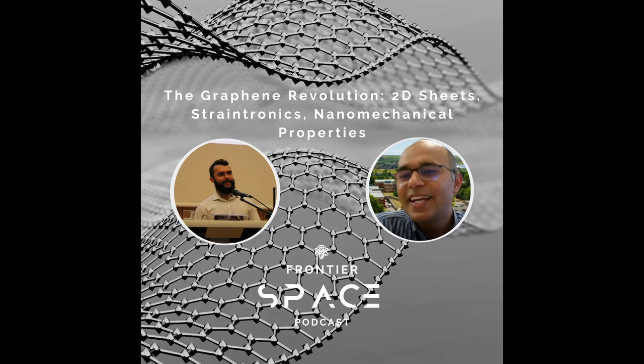So if you increase the structural disorder, the temperature will rise, but there should be a limit, because it is eventually a carbon material, and when you're heating in air, you might not be able to reach up to 500 degrees centigrade, because it will degrade the material itself. But with the optimized number of defects, we got a sustainable graphene heater with a tunable amount of structural disorder, and of course very regulated potential bias.